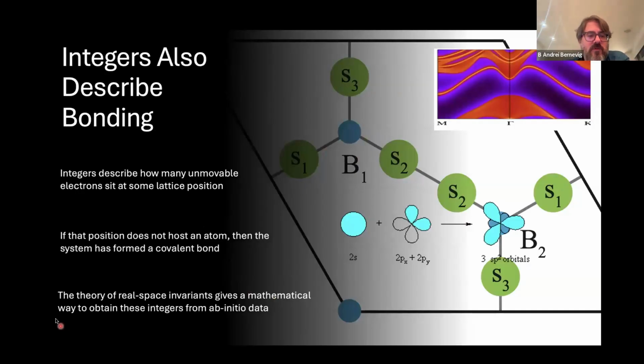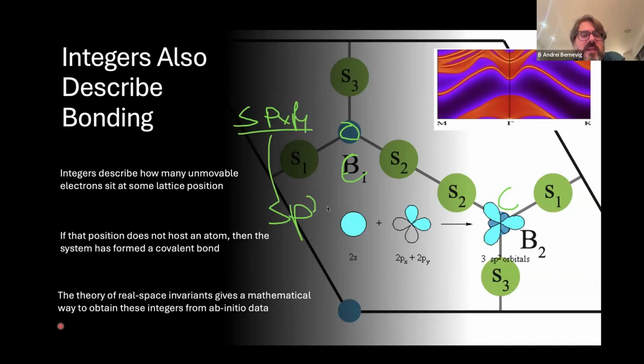So these integers, actually, for people who are doing more chemistry in the audience, can really also describe bonding of atoms. So for example, here I'm putting two boron atoms, but they might actually be carbon. Let's just put carbon because it's easier. So just graphene, for example, the same thing. Boron and carbon have similar properties in some compounds, but let's put carbon atoms here. And what we know about carbon atoms is that they have s and px, py orbitals, and we know that they have the concept of sp2 bonding. sp2 bonding just tells you that these atoms like to sit in an environment that has C3 symmetry, meaning there's three bonds at 120 degrees from each other.